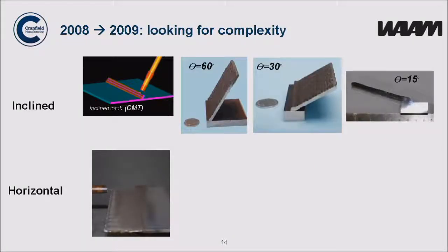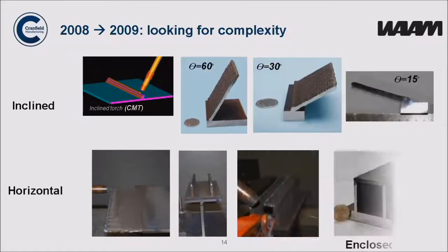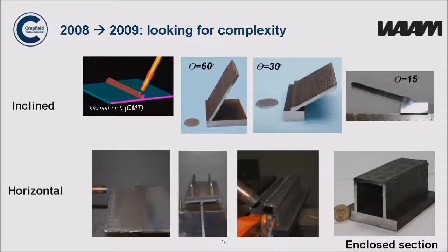And we also investigated what kind of build angles could you use. There's no particular reason why you need to build downhand. So you can see here we build at 60 degrees, 30 degrees, and horizontally. And this means, in fact, you can make enclosed structures without actually moving the part. So it's actually pretty flexible. I mean, a normal welding engineer would not be surprised by this because, of course, we weld in all positions. But if you talk to the additive manufacture community, they are very surprised by this.